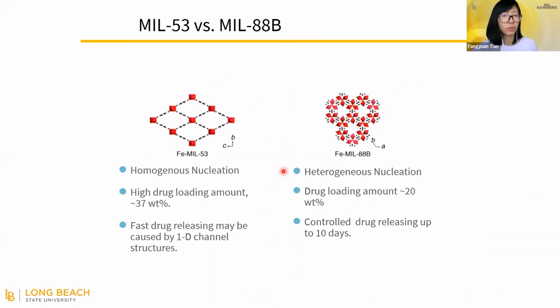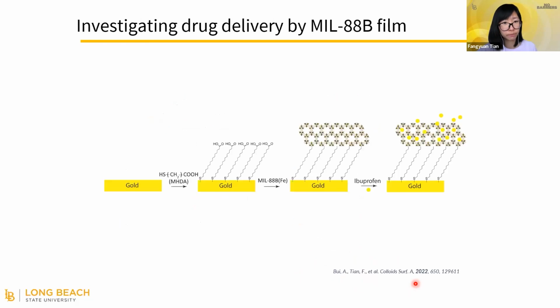So a quick comparison between those two materials: they could be synthesized through either homogeneous or heterogeneous nucleation. MIL-53, because of the one-dimensional channel, although it has a higher drug loading amount, will also release the drugs much faster compared to MIL-88B. So MIL-88B has a controlled drug release up to 10 days. So we decided to go with MIL-88B and functionalize it directly on the surface and see if it could potentially be used as a drug-eluting stent coating.